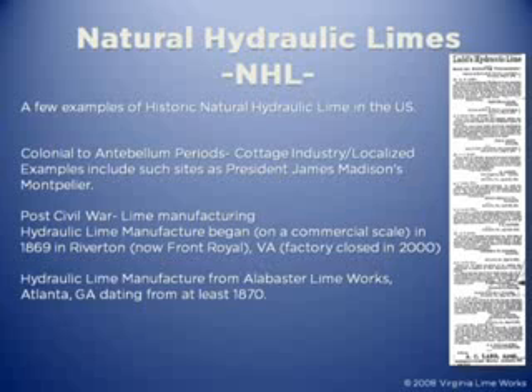So pre-Civil War, you're looking at a cottage industry, localized examples. James Madison's Montpelier, a project that we just finished up. We did quite a bit of research into the original limes that were produced there. That was an argillaceous limestone, so it had a certain amount of silica and alumina in the limestone matrix. And we actually produced a hot lime mortar from the actual same stone that Madison was using. It was a fantastic project.